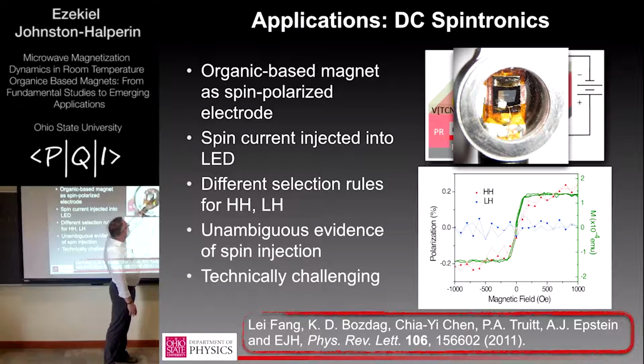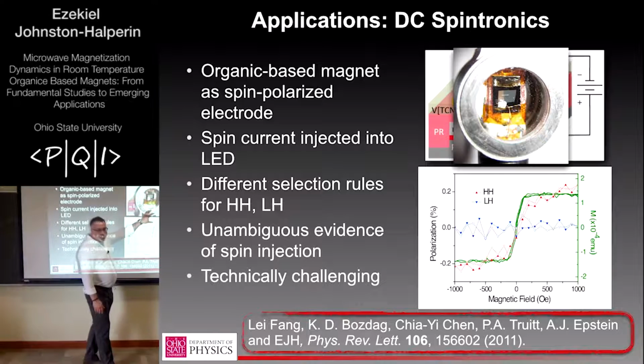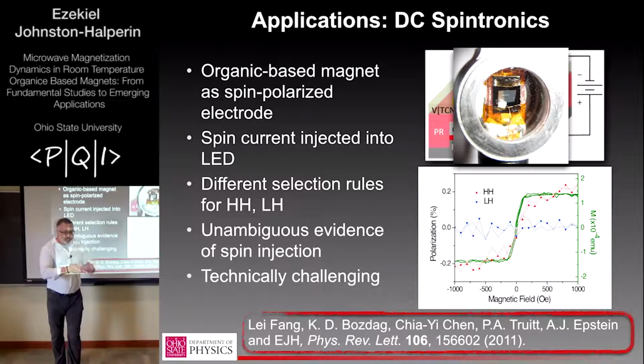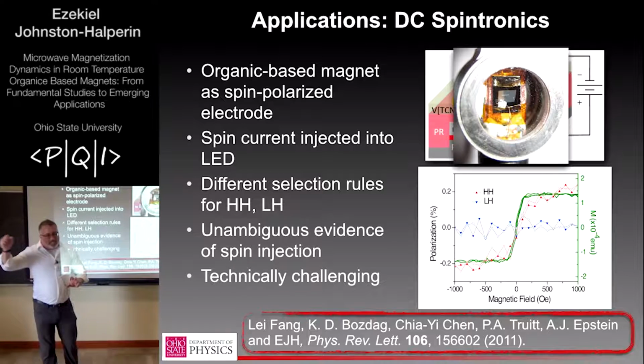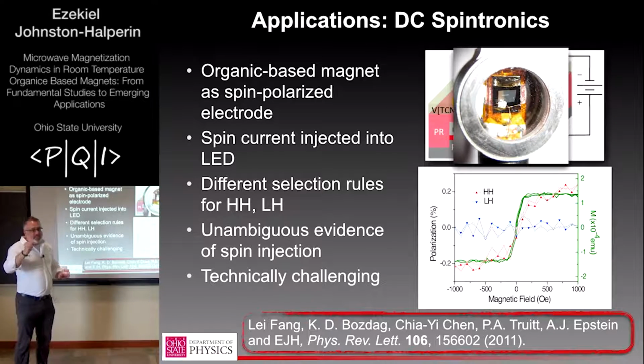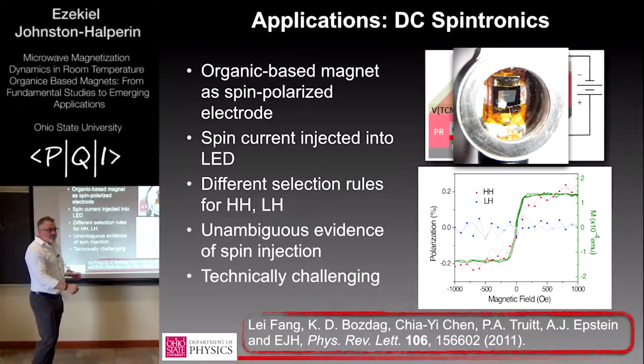Then we put down a layer of aluminum, because aluminum on VTCNE is a relatively happy deposition. But the aluminum isn't as conductive as it could be, so as a final step we put on a little strip of gold and an indium bond, which goes to feed-throughs out of this can. This can has windows on it, so we can seal it up in the glove box, take it down to our cryostat, attach it to a stick, drop it down, and do the measurement.